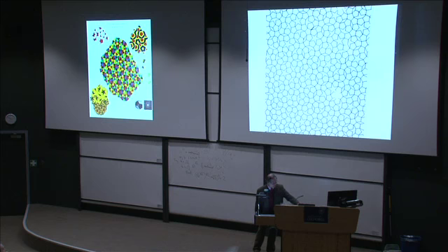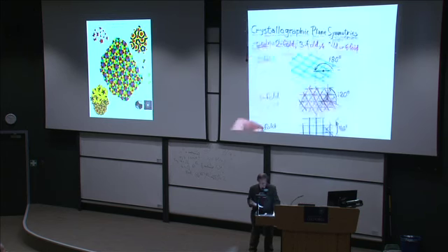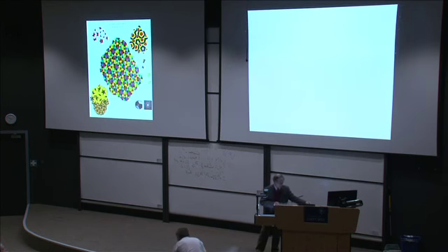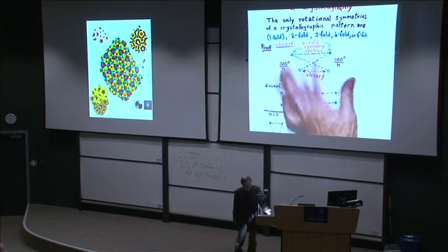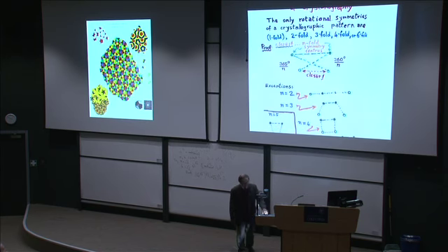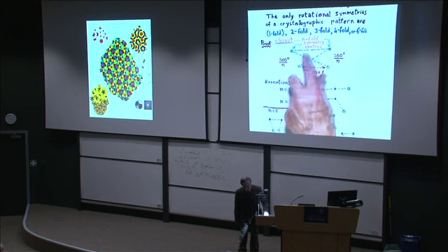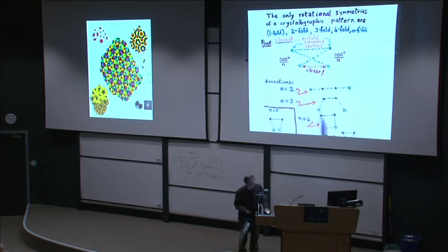Well, now you might go back to the original argument and say, what goes wrong with the argument? Let's take it so that we're looking at not exactly symmetric points, but points which have the symmetry to 99.9% or something. The thing is that if those are 99.9% points, these ones are likely to lose just a little bit of symmetry, because this one's only 99.9, that'll probably be 99.8 around.